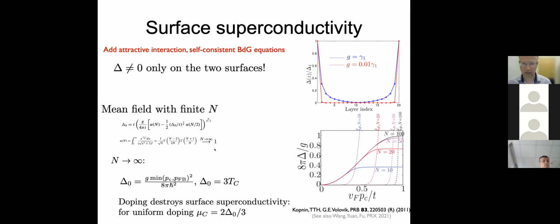You can actually solve this analytically, but the result is a bit complicated, so I will not go too much into detail. But the bottom line is that if you take a large number of layers, you get a linear scaling between delta and the coupling strength, which is here G. And the size of the flat band then appears, so it's this flat band squared. You can study the dependence on doping, for example. You can show that it destroys surface superconductivity for a certain critical doping and so on.